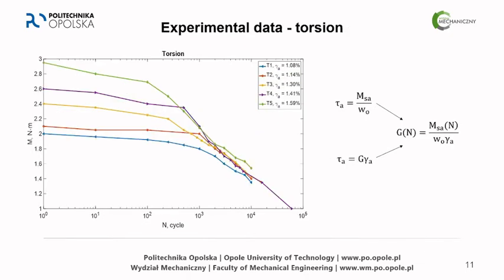And here you can see a very similar graph. However, here we have torque as a function of number of cycles, and here there's another very interesting fact, let's call it observation, that when we get to the 10,000 cycles, no matter what the strain amplitude is at the beginning, the torque is actually equal no matter which strain amplitude was at the beginning. And on the right of this page, you can see our formula suggestion for the shear modulus.